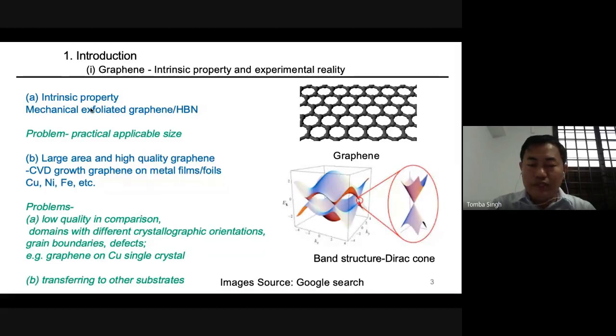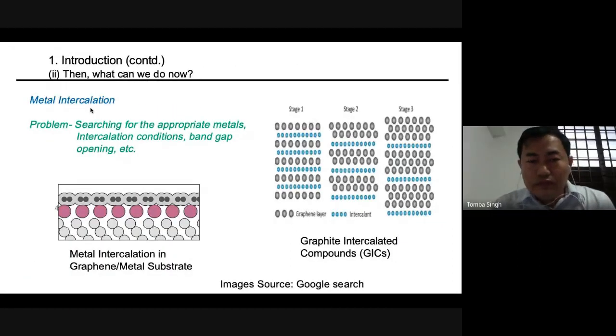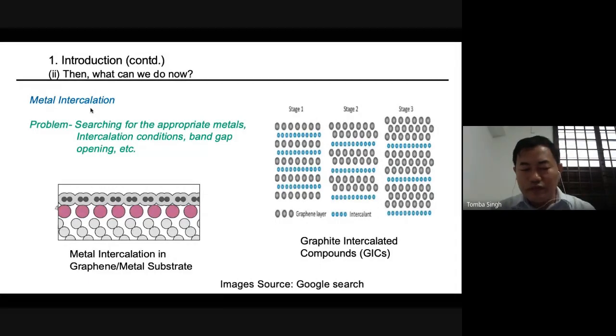Now the story does not end here, we have to transfer it to another substrate. In this transferring process, we have to dissolve the copper substrate or copper foil, then transfer it onto another substrate. In this transferring process, much tearing and many defects are introduced. So in every step, there is a problem, and the intrinsic property of the graphene is much affected. Then, is there any solution for this? We have used one technique. That technique is what we are going to see in this work.